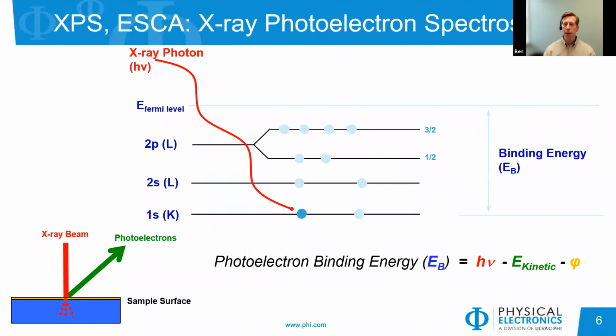So to start with, I'm going to start with XPS, which is X-ray photoelectron spectroscopy, also known as ESCA, or electron spectroscopy for chemical analysis. The general outline of this technique is it uses the photoelectric effect in that an X-ray photon, typically a soft X-ray, about 1400 eV photon energy, will strike the surface, and that will be absorbed into the sample and emit a photoelectron from a core energy level. And that photoelectron will have a kinetic energy as it passes through the sample. It will lose some of that energy through collisions and then be ejected into the vacuum. And we can collect that photoelectron, measure its kinetic energy, and then based on the photon energy, back calculate the binding energy of the orbital where it was emitted. And so from that, we can get a fingerprint of the element and composition within our sample.